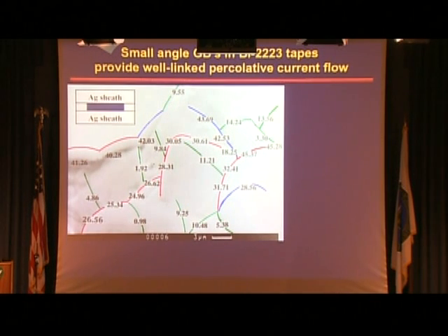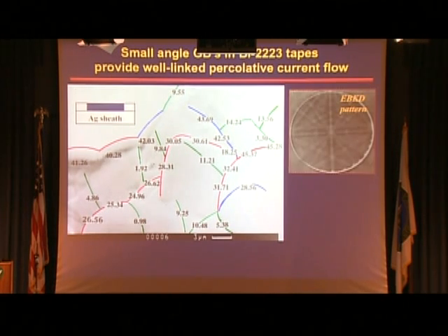And the next question was, are these grain boundaries in this bismuth-based 2223 somewhat special that they don't get disrupted so fast, because you do have some capability of carrying current? So you're looking at a cross-section, silver all around, bismuth 2223 inside. We said, let's take a look at these samples. We removed the silver from one side, took an electron beam, and looked at the orientations on the surface of the superconductor, calculated the misorientation of interfaces, and color-coded the boundaries.